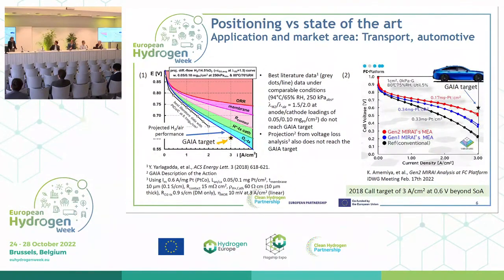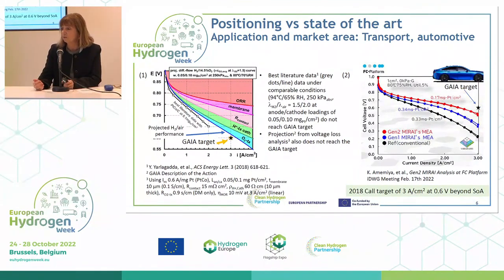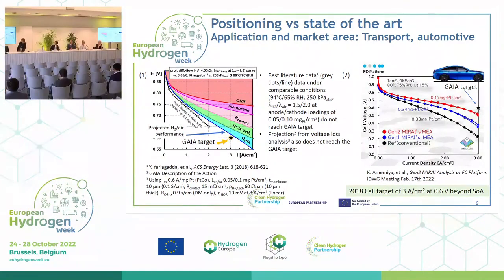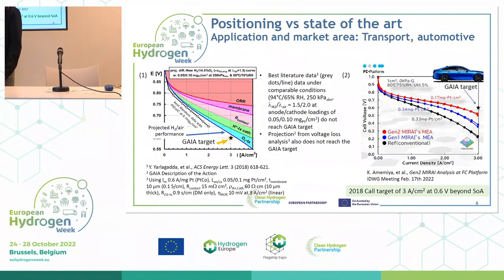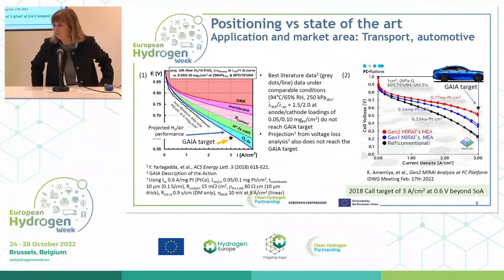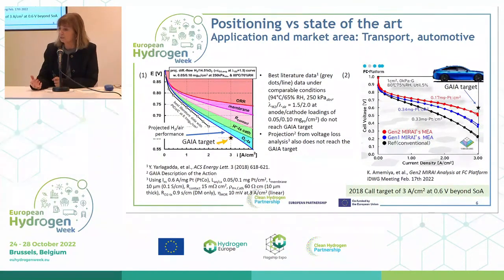And you can see that the best published data at that time actually don't allow to achieve that target. What we did in the preparation of the project was to do a voltage loss analysis, and those are the other lines that are on there, considering all of the various resistances from the various components and interfaces. And in fact, when you do the calculation, the voltage loss analysis projection is that blue line there. So once again, even with the expectations of the materials that could be prepared and their resistances and the interface resistances, even that projection doesn't allow to achieve the GAIA target.